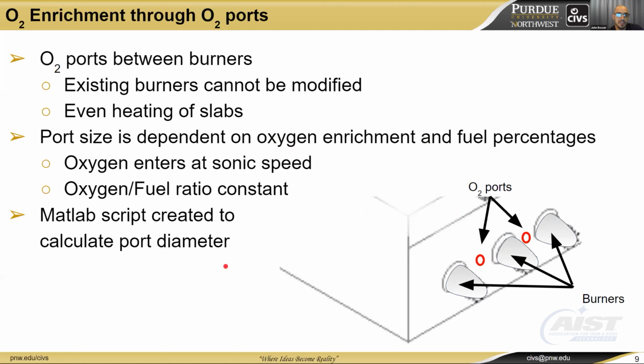The port size is dependent on the oxygen enrichment and fuel percentages. Oxygen is also injected at sonic speed because we want the reaction to take place deep into the furnace and away from the burners. And we also want to keep our oxygen fuel ratio constant. Now, these constraints are important and determine the diameter size of the ports. So my partner and I created a MATLAB script to calculate the diameter for any given oxygen enrichment percent and fuel percent.